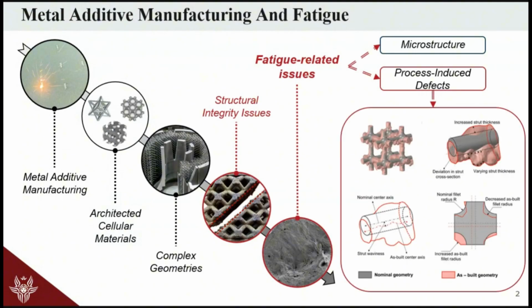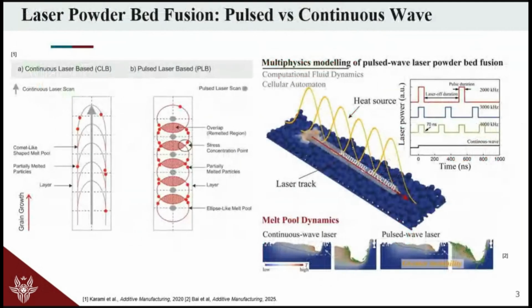These defects are mainly related to the differences in between the as-built and as-designed geometries. And these encompass, for instance, enhanced surface roughness, parasitic masses, and drosses at the lower skins. Given this, when we're dealing with metal additive manufacturing, most of the times we are talking about laser powder bed fusion, which is one of the most industrially ready technologies.